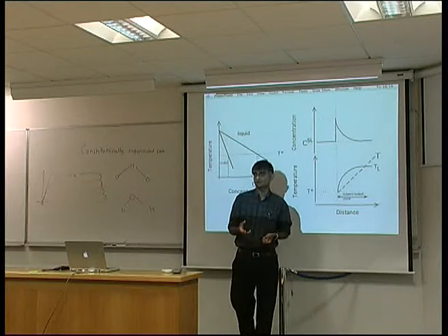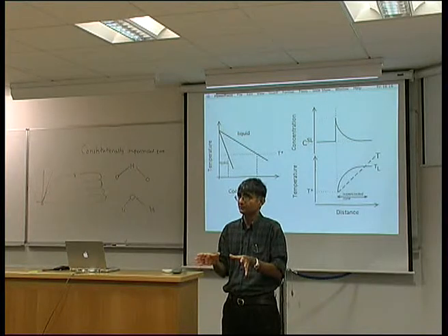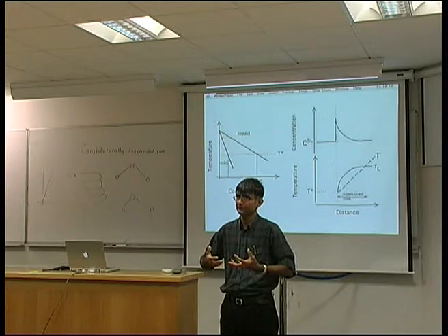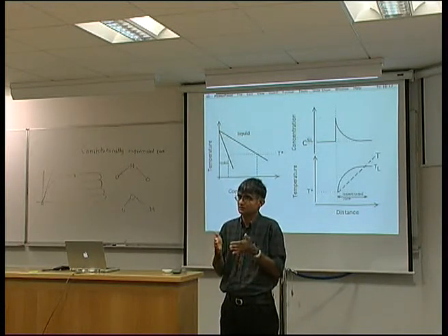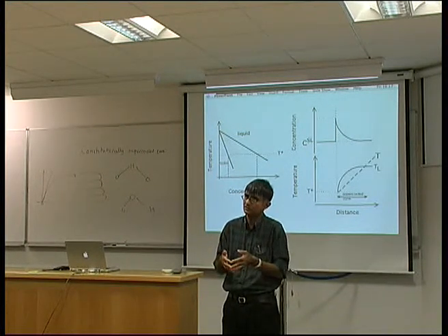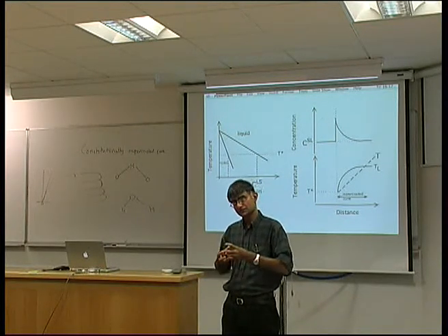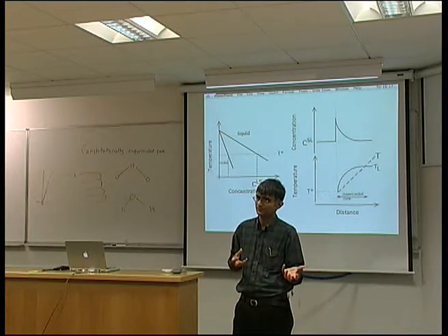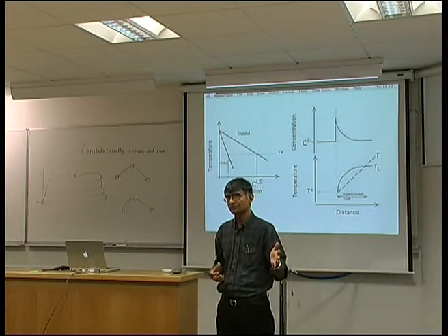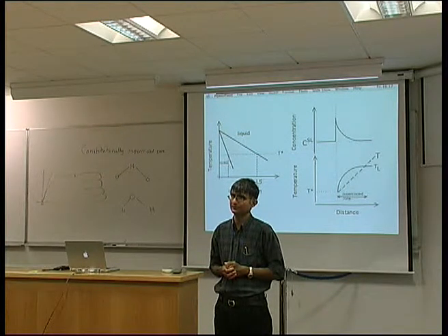With solidification, there's another factor, and that is that when it happens very rapidly, you will also have to take account of heat diffusion, because you are releasing latent heat of solidification. But you will get growth of the interface being controlled by diffusion, whether it's heat or solute, even if it's branching. Of course, if I freeze it very rapidly, then I will trap the solute in the dendrite. And in that case, the interface is moving faster than solute can diffuse around.